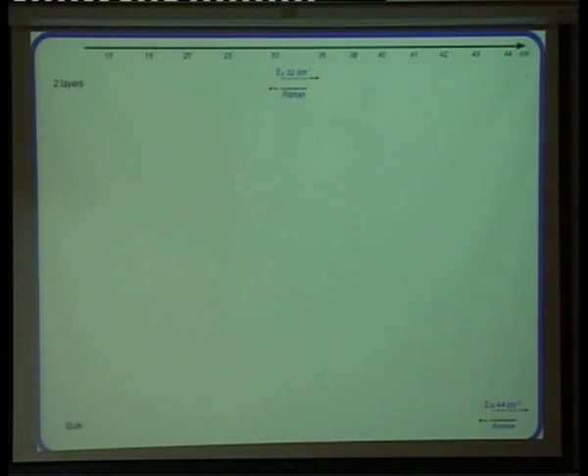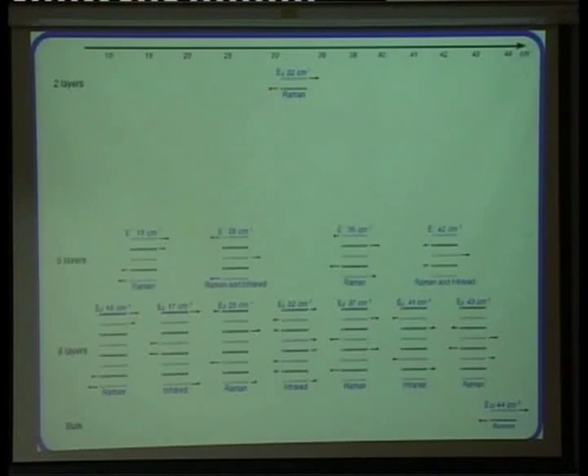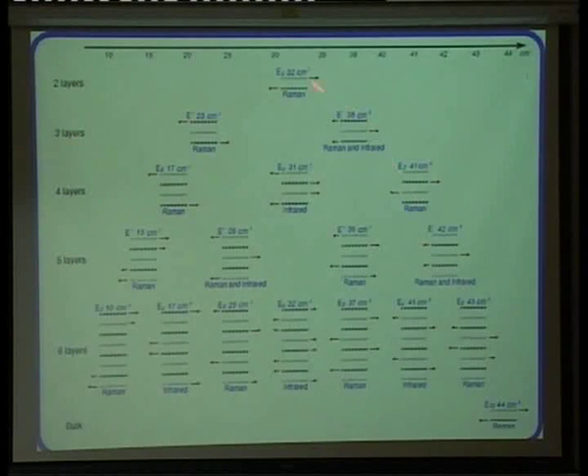The reality is that, as a function of number of layers, there are many possible combinations. And what we have seen so far is only the higher frequency one. Of course, the lower you go in frequency, for example, 10 centimeters minus 1, the more difficult it becomes experimentally. And the electron-phonon coupling, thus the Raman intensity of this mode, is very small anyway, so it's quite challenging to measure them.